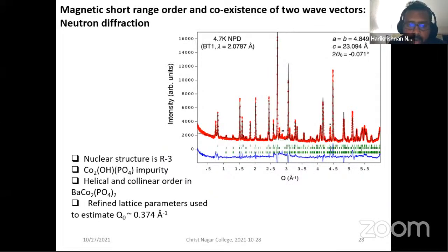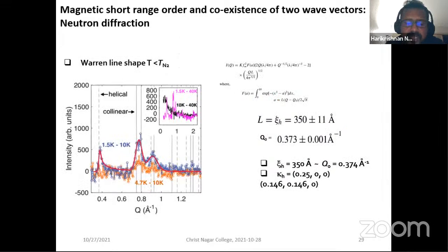Inside this material, cobalt spins will adopt two types of ordering. One is a collinear ordering, meaning that all the spins point along a line. The other one is helical, meaning that there is an ordering which looks like a helix. So you can analyze this data to find out the pitch of that helical order, or the periodicity of that, and the periodicity of the collinear order. This can be done using the data shown here, which is a neutron diffraction pattern. We find that the two types of ordering are indeed present, and their ordering wave vectors can be found. This is just like the vector analysis that we talk about.